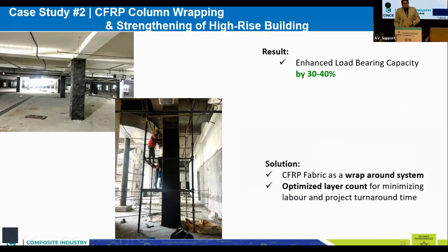The result is enhanced load-bearing capacity of the column. Typically, the numbers that come out are about 30 to 40%, because they are again limited by the core strength of the column, which is the concrete. The concrete gives up, there's nothing a bandage can do on top of it. If your bones are already broken into multiple pieces, there's nothing a bandage or a plaster can hold. So it's all dependent on the concrete strain.